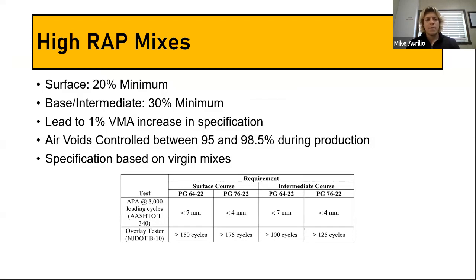So this brings me to the high RAP mixes, and in Ontario, I know we have some municipalities that limit RAP usage, and some I know have even eliminated it entirely in certain courses. But rather than work on a maximum, New Jersey uses a minimum RAP requirement because, like I said, they have a massive stockpile and they're trying to get rid of as much as they can.